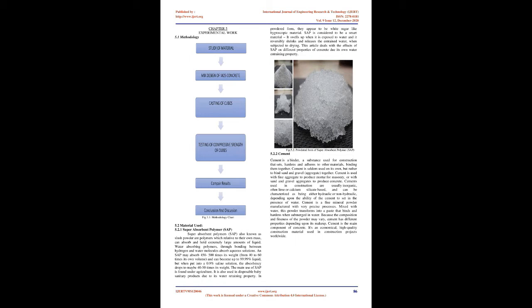Internal water curing has been used for decades to promote hydration of cement and to control the shrinkage of concrete during hardening. Saturated lightweight aggregate was previously the only material used as an internal curing agent. But there are some major problems connected to the use of lightweight aggregates for internal water curing, including difficulties in controlling consistency and significant reductions in strength and elastic modulus. These difficulties are minimized with the use of SAPs.